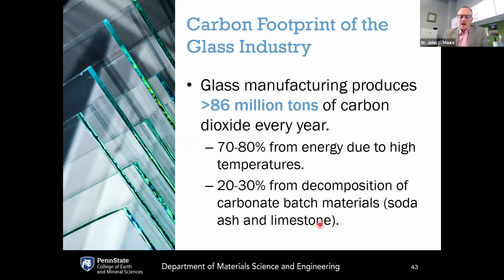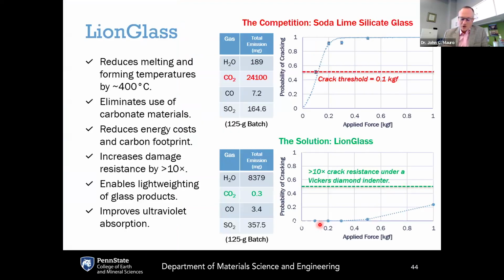And so LionGlass is our alternative to soda lime silicate. This is named after our Nittany Lion mascot here at Penn State. And what it does is it reduces the melting and forming temperatures of glass by about 400 degrees Celsius compared to standard soda lime silicate. It also eliminates the use of carbonate batch materials.